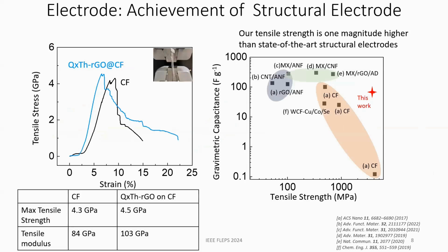Next, looking at the structural properties, here's the pure carbon fiber and then our QXTH electrodes. They have a similar maximum tensile strength, but the tensile modulus increased to 103 gigapascals, and this is because the slurry was able to bind the fibers together and reinforce it. If we compare it to other state-of-the-art structural electrodes, our tensile strength is about 1 magnitude higher, and our capacitance is still 1 magnitude lower, but it's important to note that these works did activation processes on the carbon fibers that ended up reducing the stability overall.